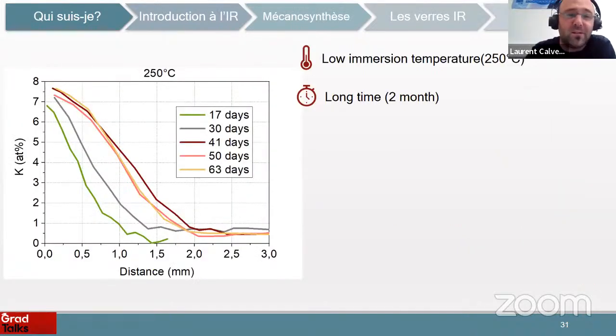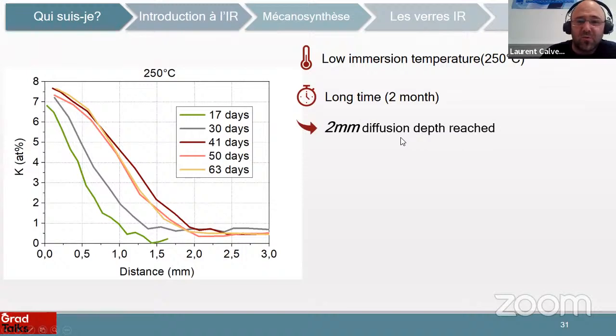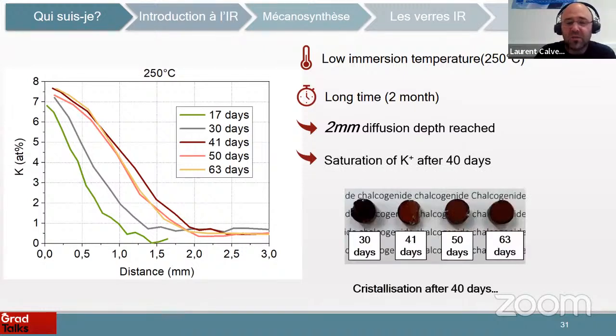And well, this method is pretty long because it takes more than 2 months to get this kind of glass at very low temperature. And for now, it's not so efficient because we obtain a diffusion depth of only 2 millimeter, but the very first publication, they only got 25 microns. So it's a pretty interesting result. But at the end, we have a saturation of potassium after 40 days and crystallization. So we can't go beyond 2 months, because then it will degrade our glass.